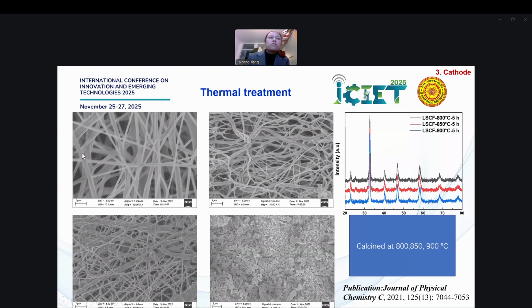And for these nanofibers, the first one on the left-hand side is the original one, just taken from the collector. Usually, for the cathode materials, we have to do all sorts of treatment at different temperatures. The temperatures we've done are 800 degrees C on the right-hand side, 850 degrees C above it, and we've also done 900 degrees C. It seems 800 degrees C and 850 degrees C are good calcination temperatures. But going above to 900 degrees C, you lose all the structures. So maybe you lose all the benefit we've got from the nanofiber. But they are all pure lanthanum strontium cobalt iron. So it gives a good